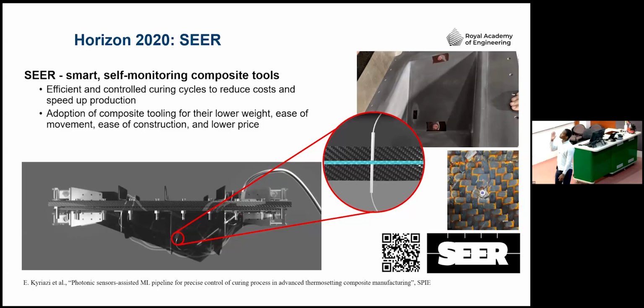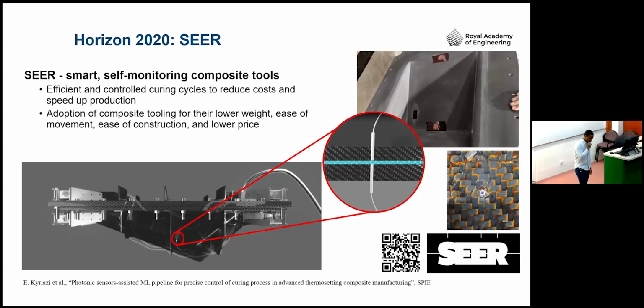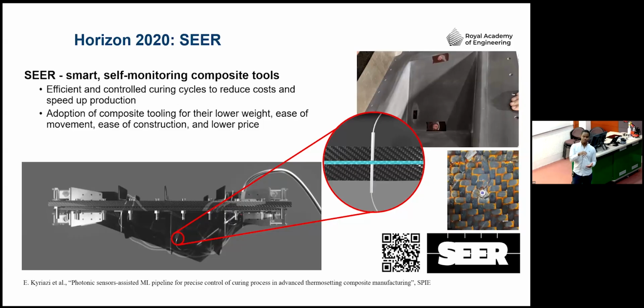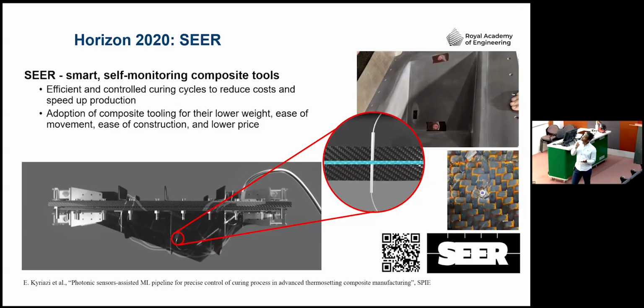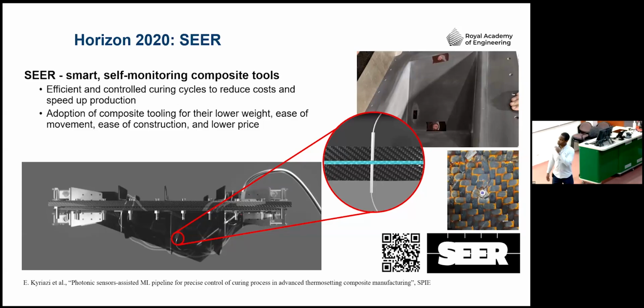So there were really, really strict design criteria. And they didn't want to drill into it because they were worried about losing the vacuum. So we decided to use through thickness punching, or through thickness reinforcement insertion, to get these sensors inside the composite, slowly parting the composite fibers. You had a bit of a compressive force of the fibers pushing back against the center, keeping everything in place, and it was able to maintain its vacuum.